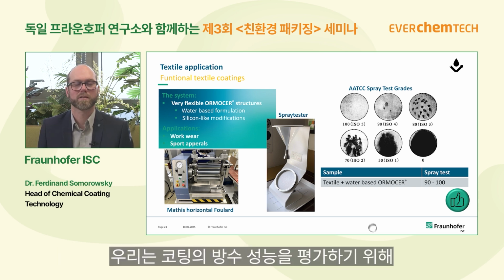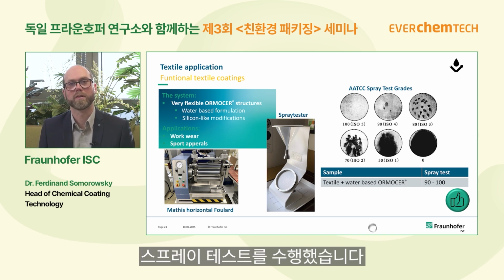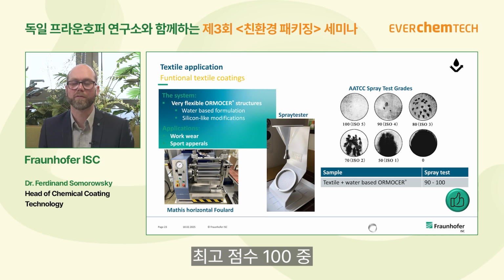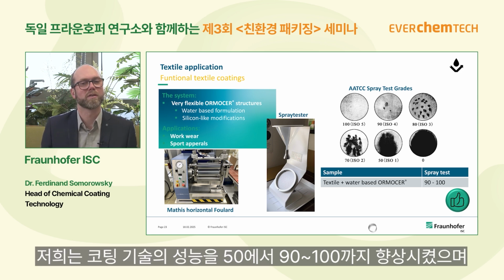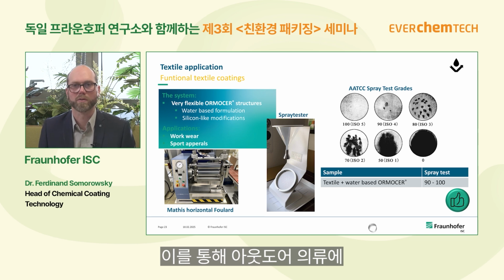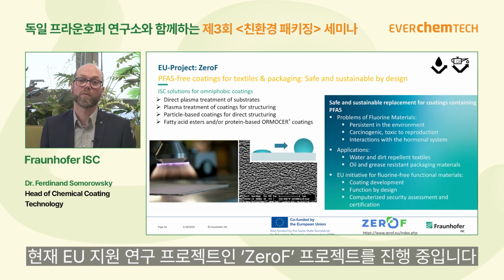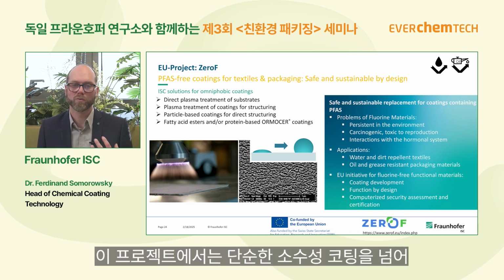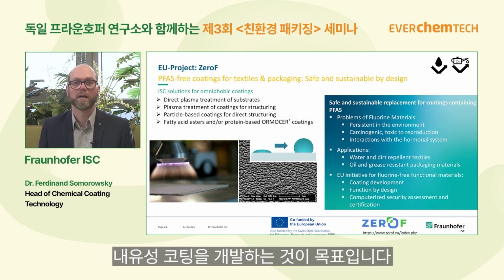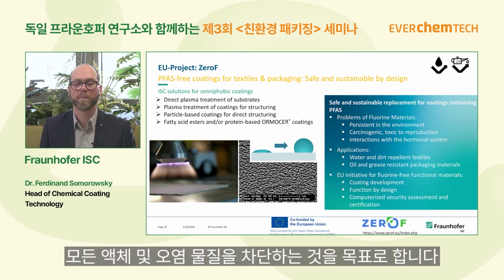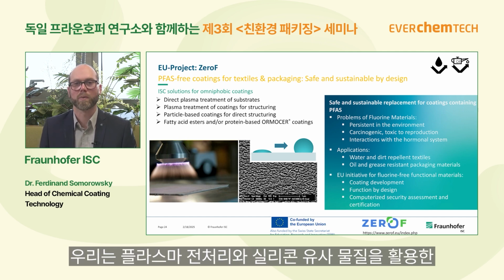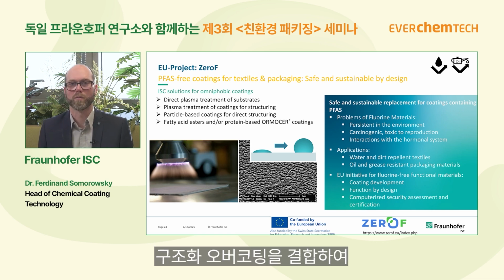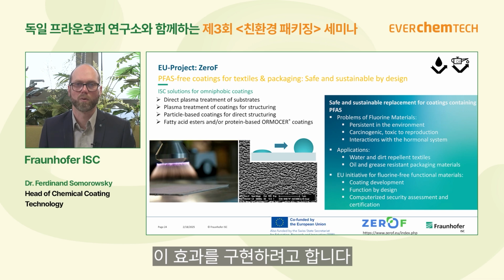And we look at the spray test, a very distinct test to prove water repellency of the materials. We can achieve values between 90 and 100, and 100 is the best value. So we can improve from 50 to 100 and equip outdoor clothes with such functional coatings. We also have an EU-funded project, and here we do not only develop water-repellent and hydrophobic materials, it should also be omniphobic. So everything that is on the textile should be repellent, and we try to achieve this by a combined plasma pretreatment and an ORMOCER overcoating with a structuralization, also silicone-like materials.